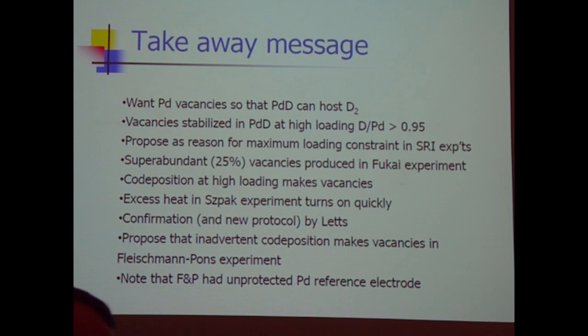For Fleischmann and Pons, replacement, we're using palladium as an electrode also. They used palladium as their cathode to load, and then they had a second palladium reference electrode. And the idea is to measure the loading by measuring the voltage difference between the cathode and the reference palladium electrode. And that was the source of the additional palladium? According to me, I'm arguing that, that's the proposal: an unprotected palladium reference electrode would supply palladium that could be co-deposited.